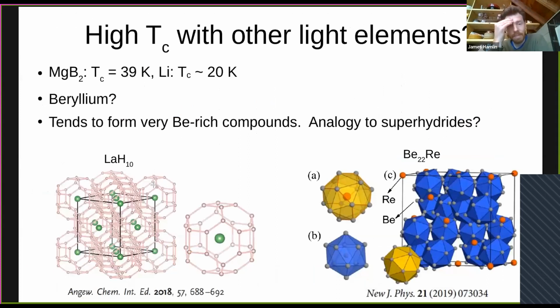And so what we decided to look at were beryllium-rich materials. Of course, there's been work in other light element compounds like MgB2. I'll talk about that a little more later. But beryllium has this very appealing feature that it tends to form very, very beryllium-rich compounds at ambient pressure. And if you superficially look at some of these structures, they look not so different from these clathrate structures that you see in the hydrides. So we have these rheniums surrounded by cages of beryllium in this material, beryllium-22 rhenium. So the question was, if we take these up to very, very high pressure, are we going to start to see